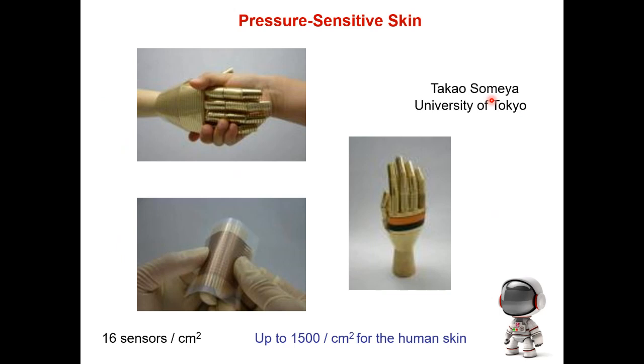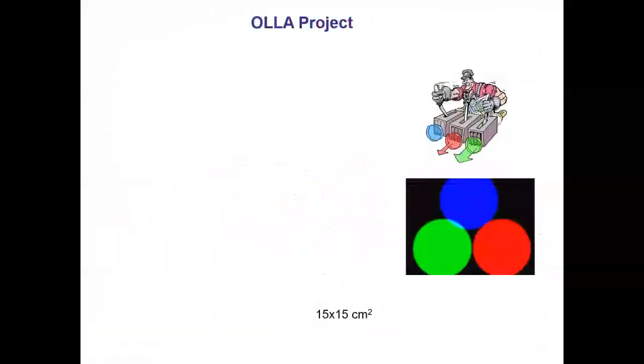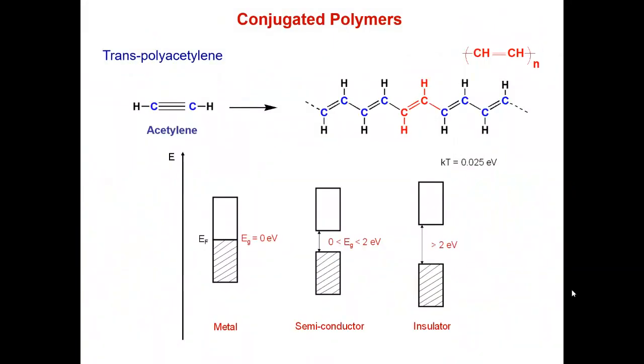You mean electrically conducting biopolymers? This is the question, right? Yeah, conductive biopolymers, yes. Okay. The thing is that if you want to get a very good electrical conductivity, you need a conjugated path, a very well-defined conjugated path. In many biopolymers, you do have a lot of conjugated electrons because you have a lot of carbonyl amide functions. But the thing is that they are not connected together. They are always like side chains, and there is no full pathway for electron transport. If you want them to hop from conjugated groups to the neighboring one, then it will be extremely slow and it's not the best idea.